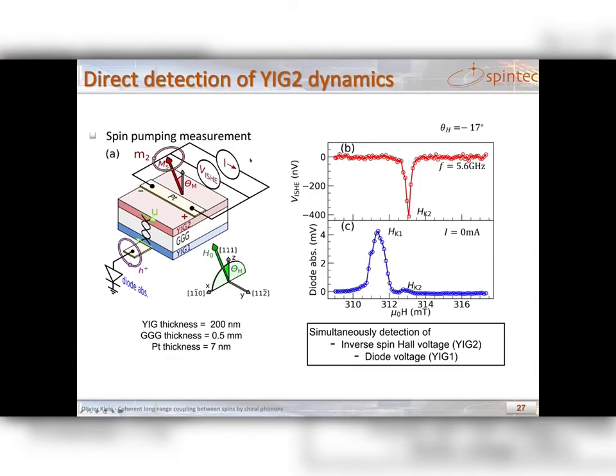To do that, we need a way to detect the top layer dynamics. Okay, so what we are going to do is put on the top layer a 7 nanometer platinum stripe, and we are going to use the inverse spin Hall effect to detect the spin pumping signal. Okay, and this will give us an idea of the power dissipated in the top layer. We can still detect the bottom layer dynamics with the microwave antenna.